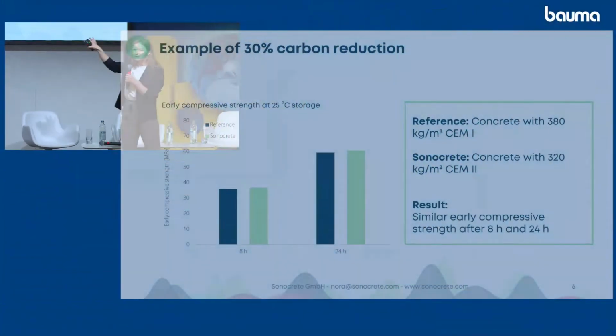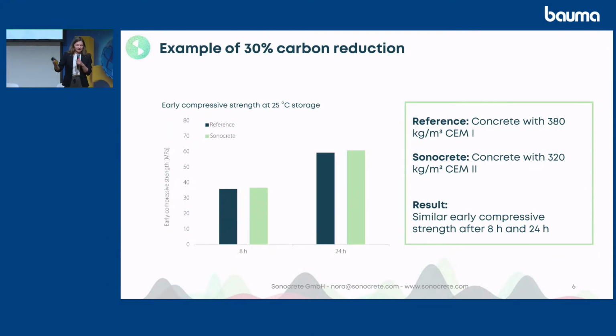I brought you an example here. It's something we've been doing with a partner just this summer. Looking at the right side first, you see where we started. The reference is the standard concrete recipe. It was using 380 kilograms of CEM I. CEM I essentially means, some of you might know it as OPC, ordinary Portland cement, but it's cement where most of it is clinker, so it produces a lot of carbon to make this. What we did was reduce this from 380 to 320 kilograms per cubic meter, and we replaced the CEM I with CEM II. CEM II is cement that only has about 60 to 70% of this clinker, the CO2-creating material, and the rest is other stuff. So that means it's basically a double reduction, and in the end that makes a 30% carbon reduction.